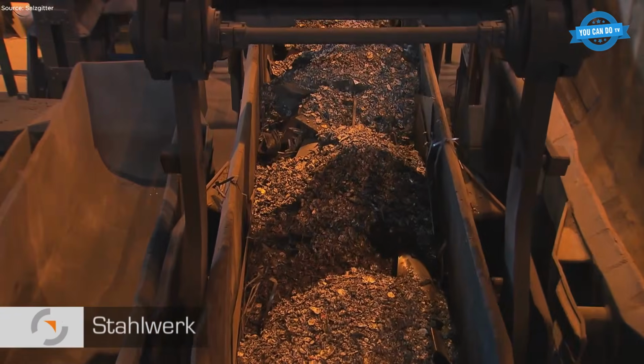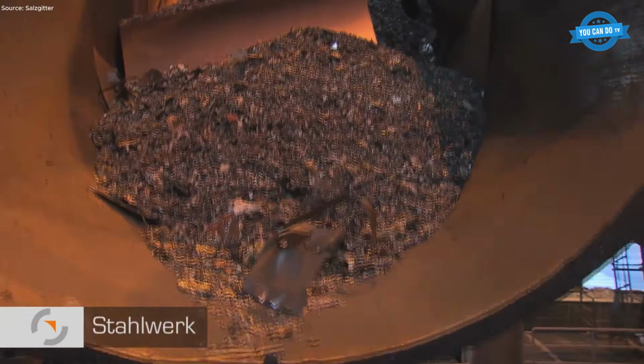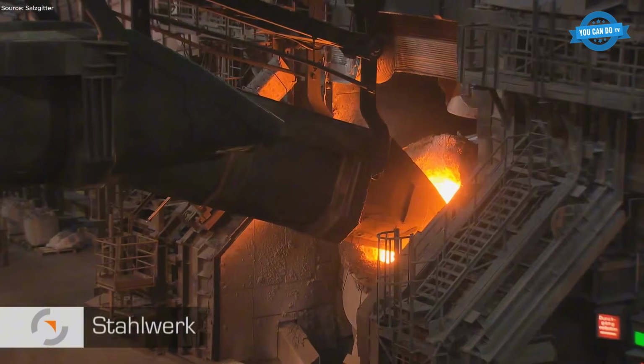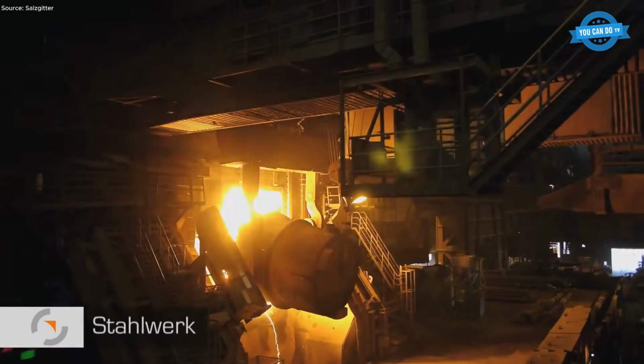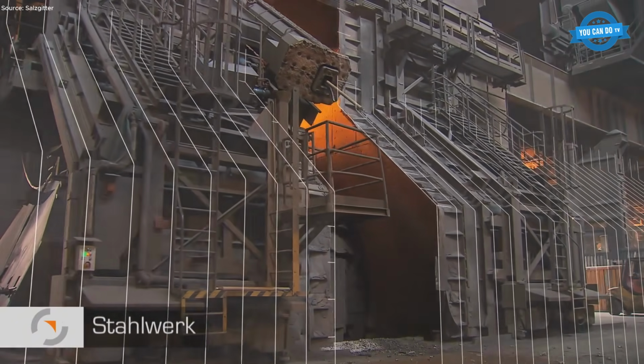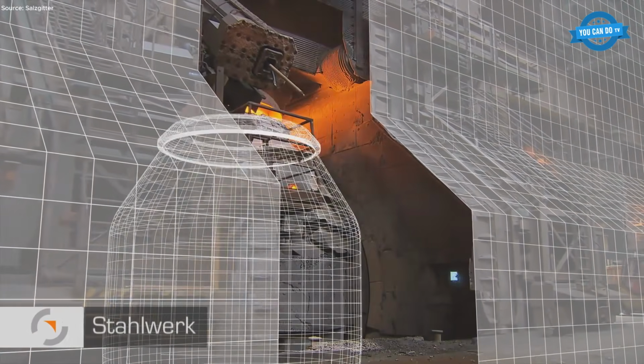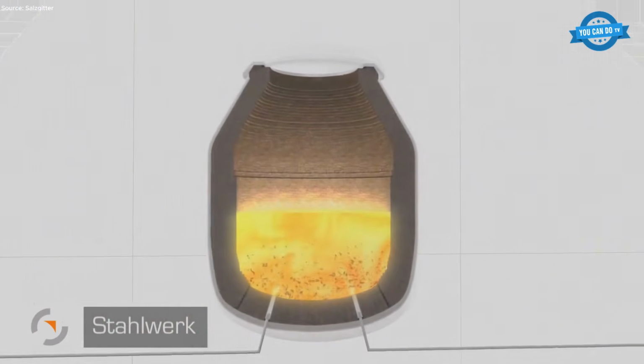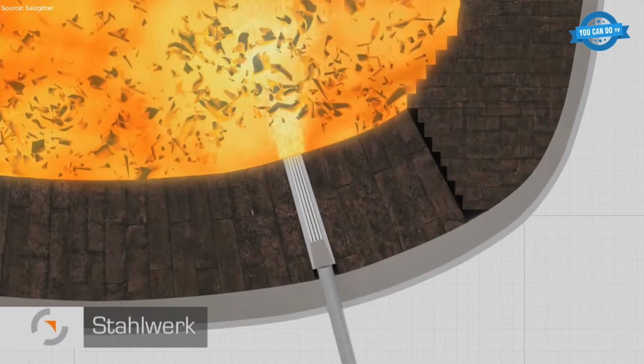After about 8 hours, molten iron and slag accumulate in the hearth. Every 2 hours, the tapping process releases liquid iron at roughly 1450 degrees Celsius, while slag is separated. The hot metal is transported in torpedo ladle cars to the steel plant.